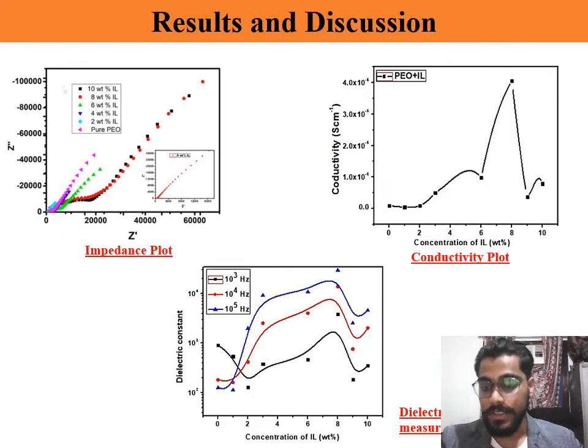Now we can see from the result and discussion part, the Cole-Cole plot of the impedance spectroscopy at room temperature at a high frequency region was plotted on varying weight percent of ionic liquid ranging from 0 weight percent to 10 weight percent concentration in PEO matrix as shown in the figure. We can see that a semicircular spur is seen followed by a spike at a very steep rate towards the lower frequency region. The semicircular spur at a high frequency area corresponds to the parallel combination of bulk resistance and capacitance of SPE freestanding films. The bulk resistance attributes to dielectric polarization and ionic movement in a polymer electrolyte. Additionally, a spike at steep rate towards the lower frequency area attributes to ion transfer near the electrolyte interface.